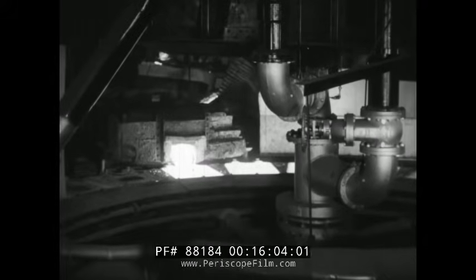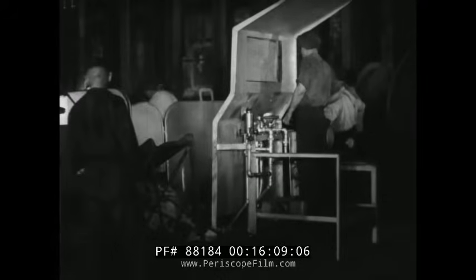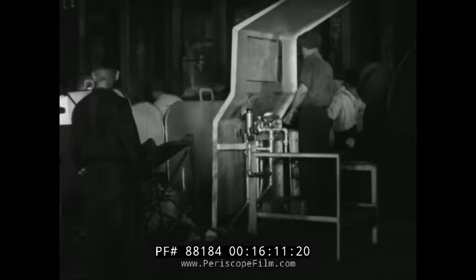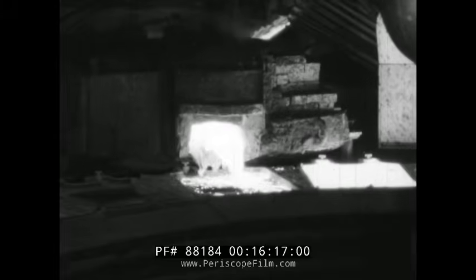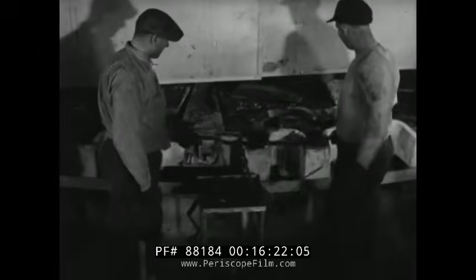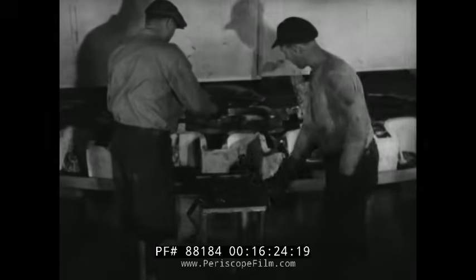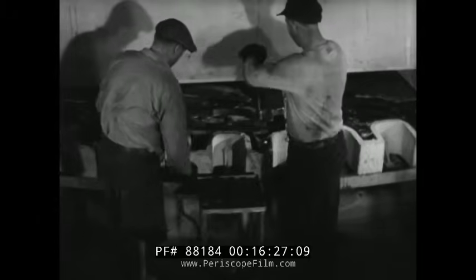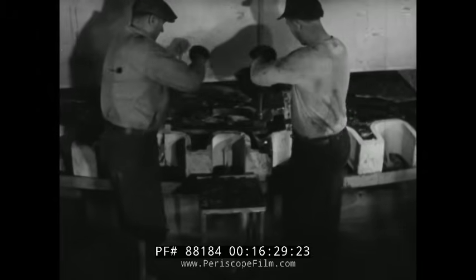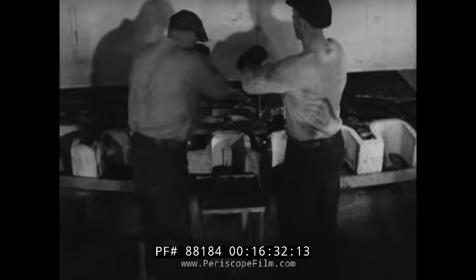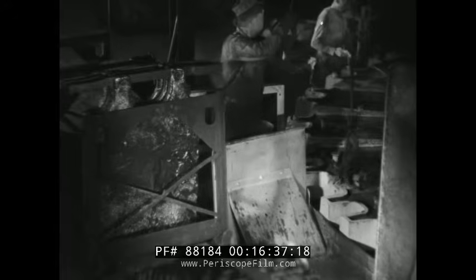The holding furnace is tipped and the molten metal pours into the molds. The casting wheel is controlled by a trained operator. Each anode is equipped with a heavy bar to support it in the electrolytic tanks and to form an electrical contact. The finished anode is removed from the casting wheel.